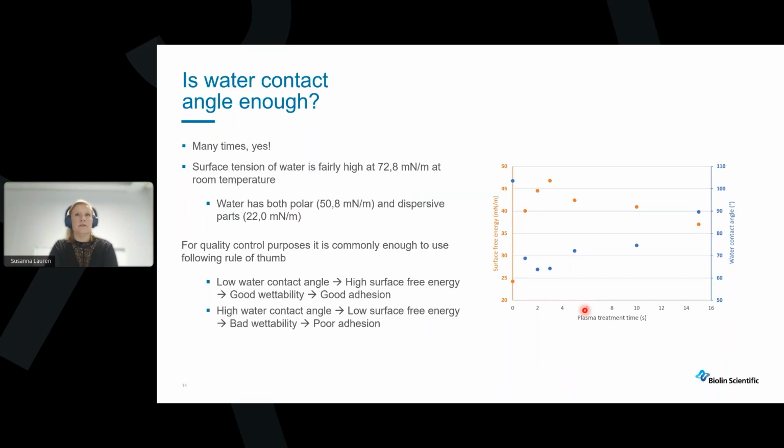Here you can see that when the water contact angle is at its lowest, the surface free energy is at its highest. So we can also use the water contact angle to define our plasma treatment times.